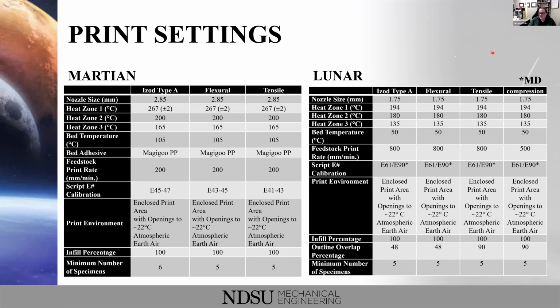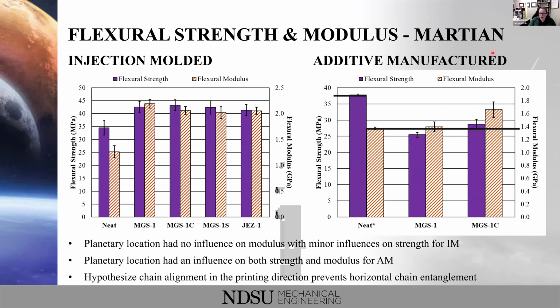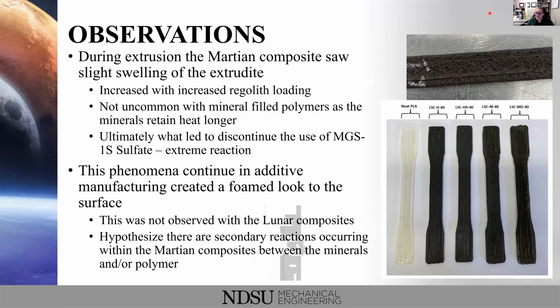The biggest thing we had to control was the slicer that we're using. So we're using Simplify3D. It wanted to put the starting point of every round right here in the middle of our specimen, which is a stress concentration, so they naturally will fail there. So we had to force it to start them at the top in the grip section. And that is the only thing we had to force it to do. Otherwise, our sidewalls are just what's printed.